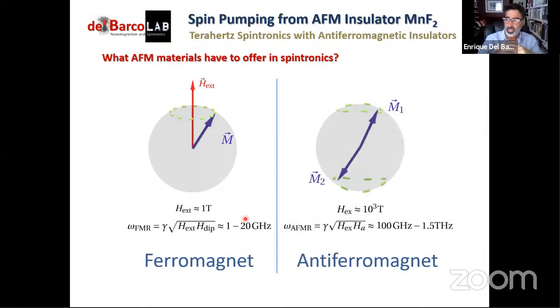And of course, the same thing happens with an antiferromagnet. But in the case of an antiferromagnet, the dynamics are governed by the exchange interaction and the anisotropy energy. Anisotropy energy is small, similar to the ones that we find in ferromagnets. But the exchange interaction, if we look, for example, at the effective exchange field in antiferromagnetic materials, can be as much as 1,000 Tesla. That is about three orders of magnitude larger than the external fields that we can apply in ferromagnets, right? So the dynamics that we expect of these polarized magnetizations are going to lie in the range between a few hundred gigahertz and several terahertz.